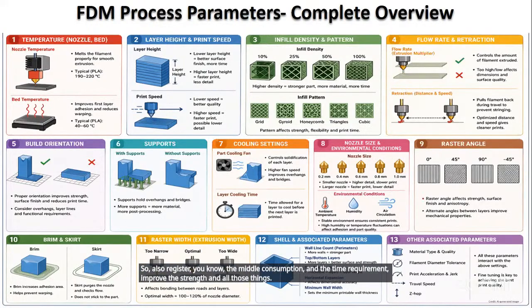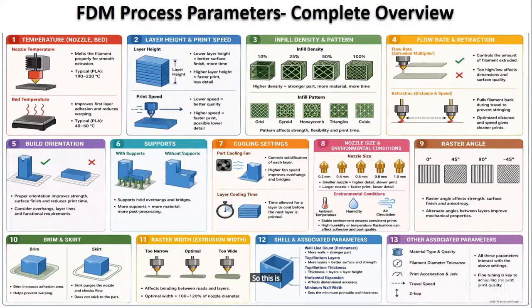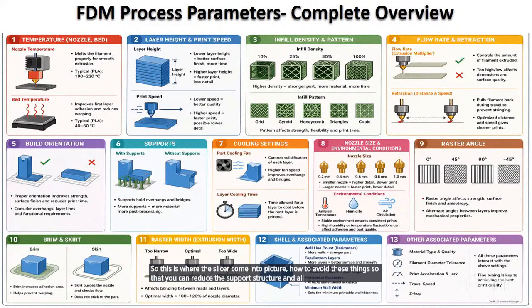And the support structure is one of the important aspects in 3D printing, because we'll be printing complex overhanging components. When you have undercuts and overhangs, we need to give the support structure. This is where the slicer comes into the picture, to reduce the support structure. Even though we have overhangs and bridges, printing without support structure is always recommended, but in certain cases we cannot avoid it. If you're giving it, then how little you can give depends on the orientation.